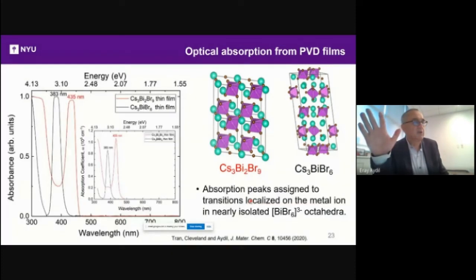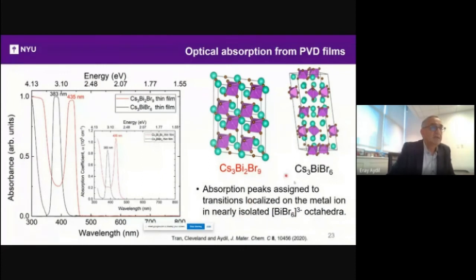Now, when we measure optical absorption from PVD films, there is no liquid, no chance of contamination from oleic acid, BiBr6 ions, etc. Depending on which material we make, if we make the 329, we get an optical absorption peaking at 435. If we make the cesium-3 bismuth bromide, we get an optical absorption at 383, okay? And we assign these transitions to localized transitions on these purple BiBr6 octahedra. Note that the 383 comes from this material where the octahedra are isolated.